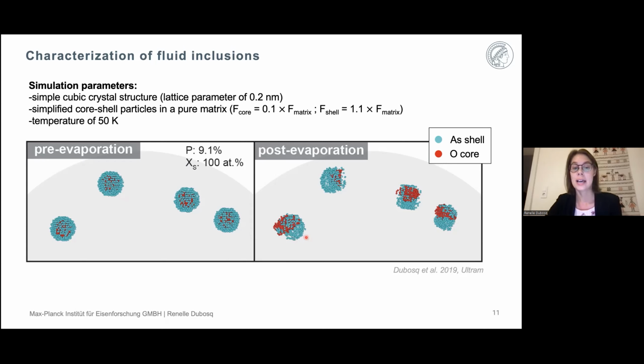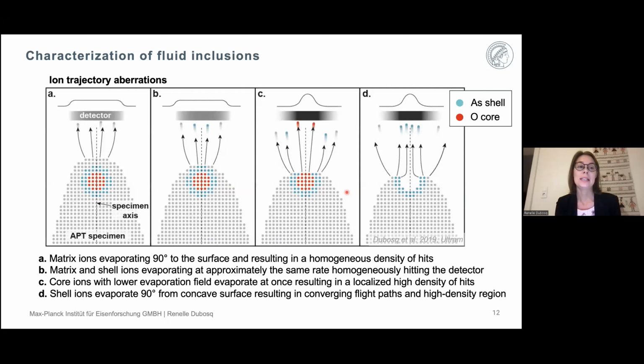Here we noticed that the shell atoms seem to have mostly maintained their spherical morphology, just with a slightly erratic arrangement of atoms. But what we notice is that the core atoms have all formed these dense disc-like shapes, either on top of these spheres or at the edges of the spheres. These morphologies and structures are very similar to what we've documented in the APT experiments. These morphologies can easily be explained with ion trajectory aberrations.